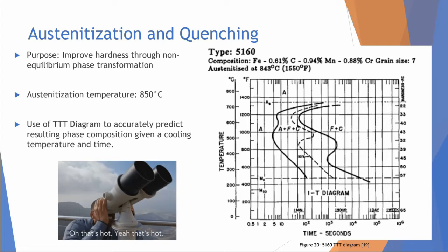After the shot blasting process, the metal is then preheated to austenitization temperature, around 850 degrees Celsius, in which the time is dependent on the thickness of the material. The quenching process can be controlled by using the time-temperature transformation diagram of 5160 steel. This diagram allows for an accurate prediction of the phase formed when cooling a specific steel at a temperature and time. For 5160 steel, a quenching process could include quenching the material from 850 degrees to 300 degrees for 5 minutes, followed by room temperature cooling.